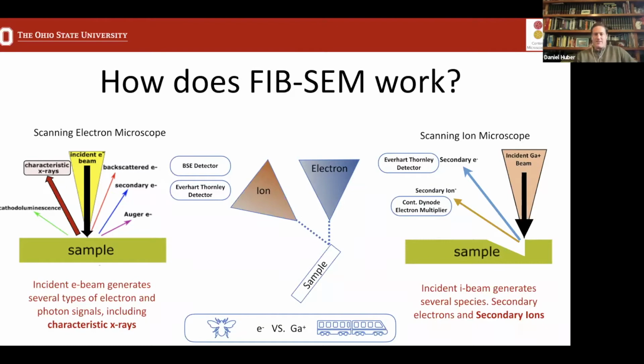The main difference here, and something that Hank and I kind of worked out one afternoon years and years ago, is if you're driving down the highway and an electron hit your windshield, and that was roughly the size of a bug hitting your windshield, how big would the gallium atom or ion be when it hit your car? And we calculated it to have roughly the mass of a locomotive. So that was the size difference, and why when you're blasting your sample with a gallium beam, you can actually remove material and not just take an image.